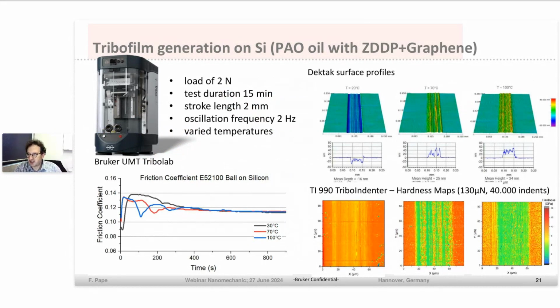Here's an example we generated at Bruker in Karlsruhe, where I took some PAO oil with ZDDP and graphene, and we investigated the friction regarding an increase in temperature from 30 to 100 degrees. And what is very nice, we can see under room temperature in the diagrams for the surface profile, we achieve some wear on the surface. And by increasing the temperature, the tribofilm increases as well, as we can see also in our model for the growth of the tribofilm.